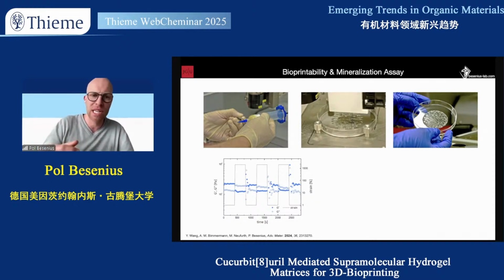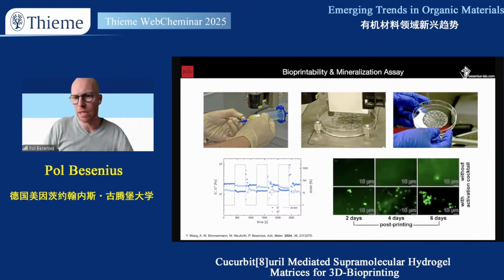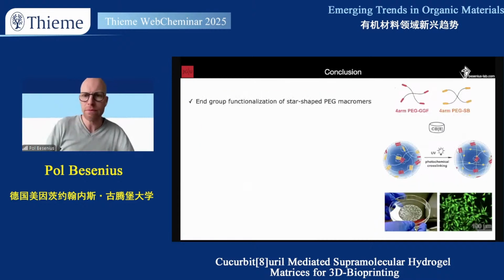And this is the reason why these can be printed. So you can prepare the material, mix them with cells, and then print in commercially available 3D printing devices. And then now these are osteoblasts, and you can do very simple activity tests, crystallization tests to see that these cells still produce calcite as they should, as osteoblasts. I'm looking a little bit at the time.